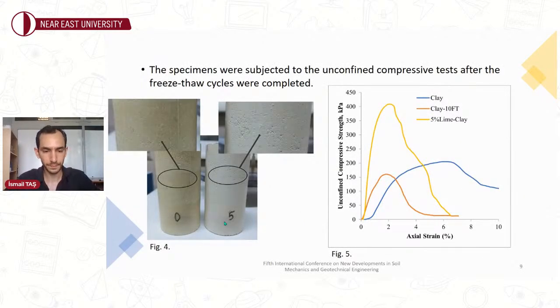And the clay soil had a strength of 205 kilopascals. After 5 and 10 freeze-thaw cycles, the strength of the clay decreased to 192 and 160 kilopascals, respectively. The strength of the 5% lime treated clay was 311 kilopascals after 7 days, and it increased to 408 kilopascals after 28 days. So we can say the strength of 5% lime treated clay increased at the end of the 7 and 28 days.